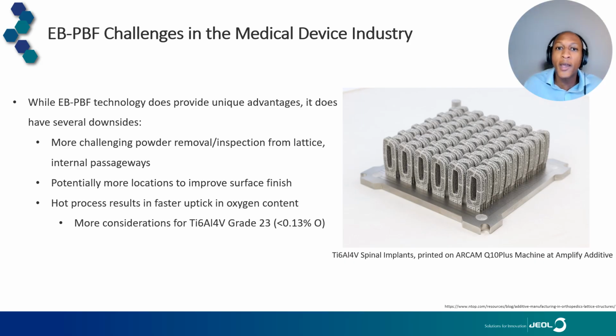Now, I did want to speak to some of the benefits of using electron beam powder bed fusion, but of course, there are challenges with any selection of technology, specifically for the medical device industry. Some of the downsides and areas for improvement for the technology, because we are sintering the powder particles layer by layer: one thing to consider when selecting electron beam powder bed fusion for the medical device industry is the challenge of powder removal. So for example, in these spinal implants on the right that we manufactured at Amplify Additive, because we are building with sintered powder, cleaning off that powder with the powder recovery system and blasting requires a bit more process control to ensure that powder is completely removed from the lattice structure.